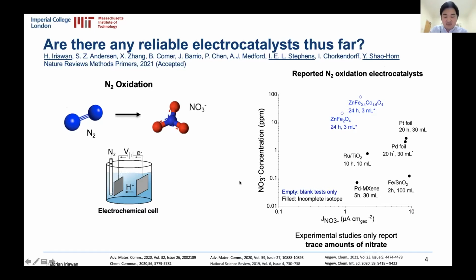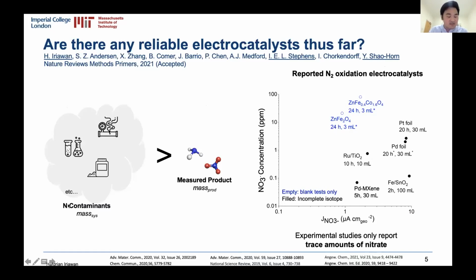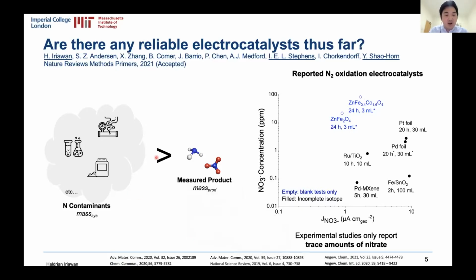However, these trace amounts of the product being detected are also quite concerning, because we know that nitrogen contaminants from laboratory settings, which can come from the glassware, gas impurities, catalyst preparation, electrolytes, the membranes, and so on, can easily dwarf the measured products, leading to false positives. So without further verification, it is quite difficult to say if these reported catalysts would work at all. In fact, in our recent review paper, we investigated the system mass and the production mass on the systems and find why nitrogen catalysis has experienced reproducibility issues.